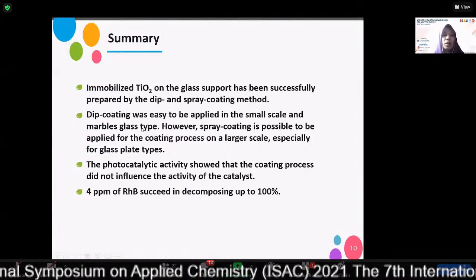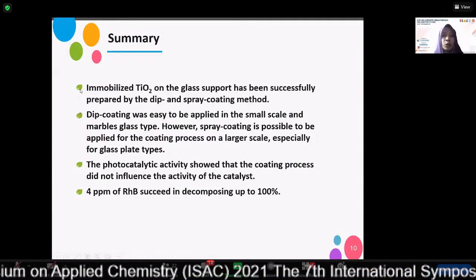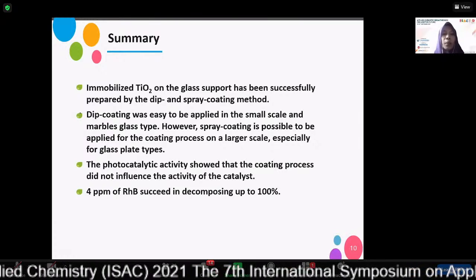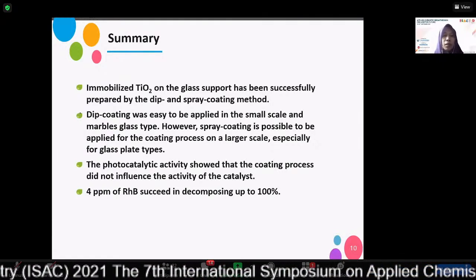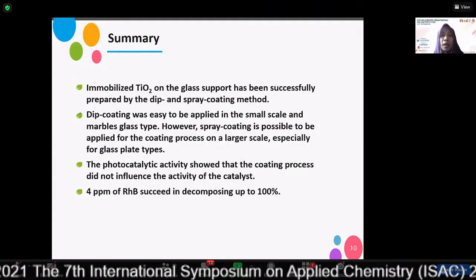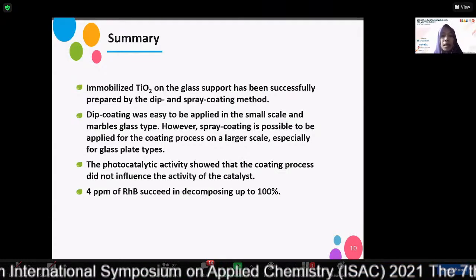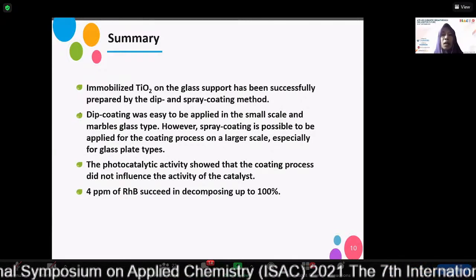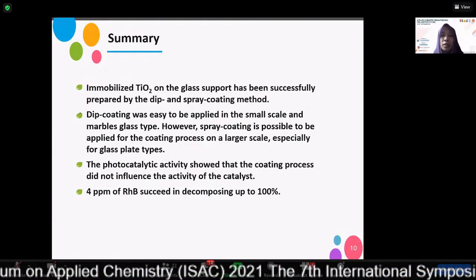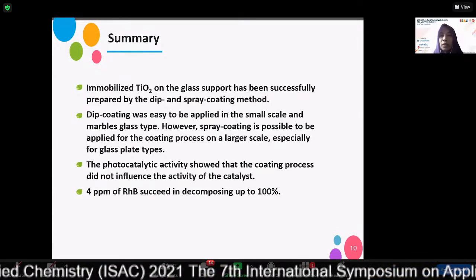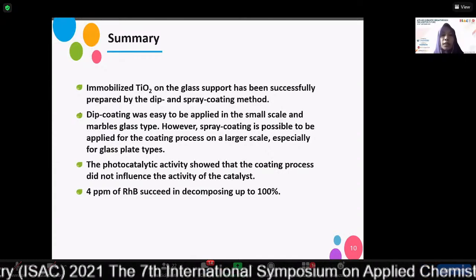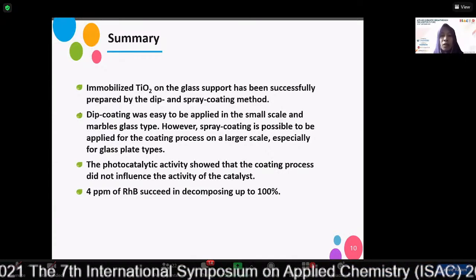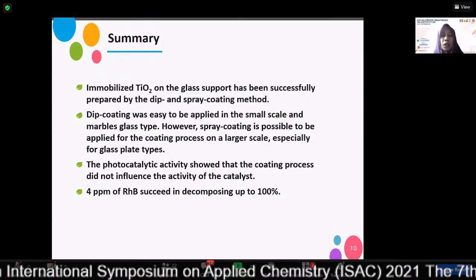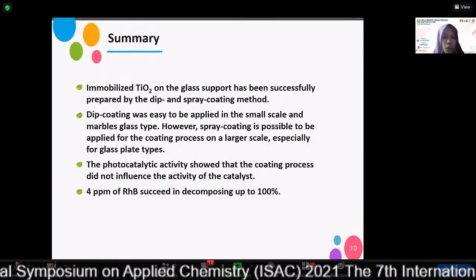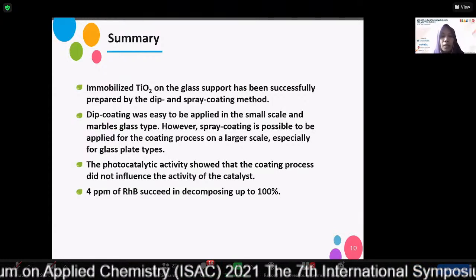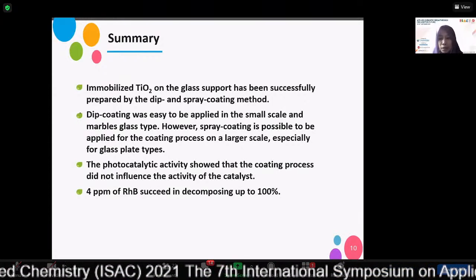The last one is the summary. First one, immobilized TiO2 on the glass support has been successfully prepared by the dip and spray coating method. Dip coating was easy to apply on a small scale and on marbles glass type. However, spray coating is possible to apply for the coating process on a larger scale, especially for glass plate types. The photocatalytic activity showed that the coating process did not influence the activity of the catalyst. And the last one is 4 ppm of rhodamin B succeeded in decomposing up to 100%.